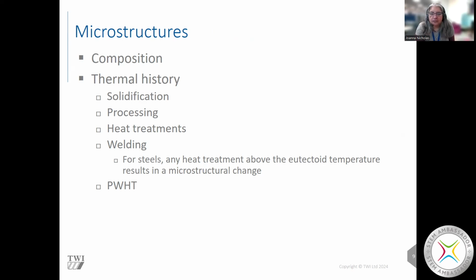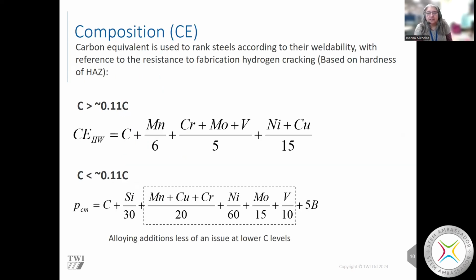And then for steels, any heat treatment that takes the temperature up above about 720 degrees C changes the microstructure. The microstructure is just how the crystals are arranged, and that can be changed as long as it's been hotter than 700 degrees C. And then we've got something called post-weld heat treatment, which also affects the microstructure we end up with, and so the hardness. To get the hardness, we need to know something about the composition and something about the thermal history.